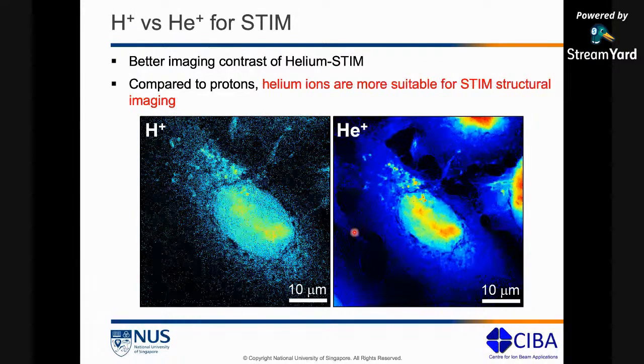Then there is a question of whether we can use protons or helium alpha particles for STIM, and of course we can use protons or alpha particles for STIM imaging. But then again, there are pros and cons to it. Alpha particles being heavier, they give a better imaging contrast for helium STIM. As you can see here, the contrast is much better. For proton STIM, because protons are lighter, we lose out on the contrast or the resolution.